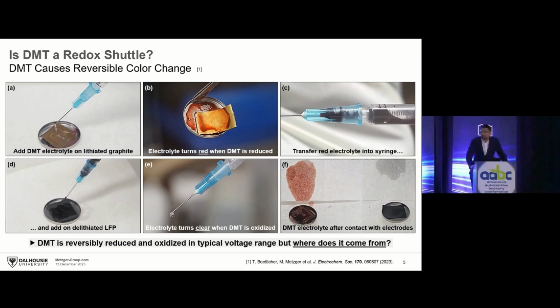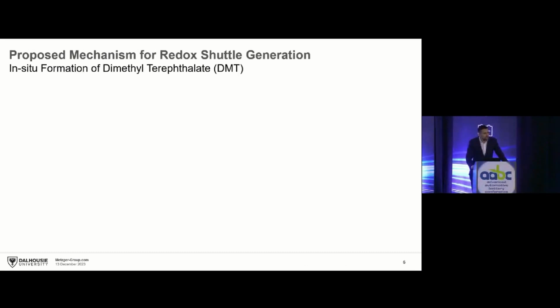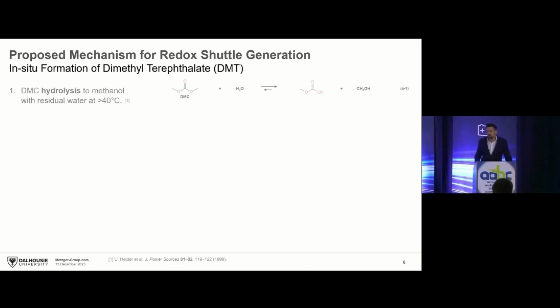But of course, the question is, where does this strange molecule in our battery cells come from? So I want to propose a mechanism for how this molecule can be created in our cells. I want to start by showing you the hydrolysis reaction of DMC. DMC is of course a very common linear carbonate used in almost all batteries. It would be the same for EMC or DEC. If you have some residual water in your battery cell, which is very hard to get rid of, we dry all of our cells at 150 degrees Celsius, but even if you do that, there's always some residual water in the cell. So especially at elevated temperatures, the DMC molecule can be hydrolyzed, and you get methanol formed in your battery cell.